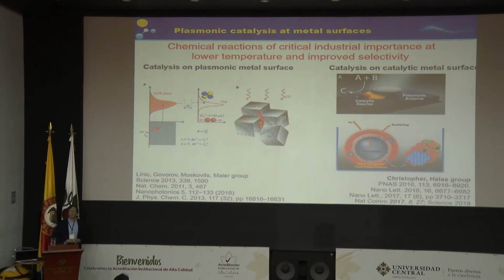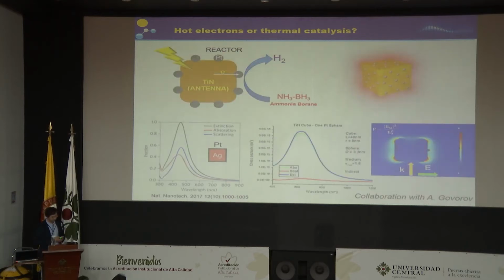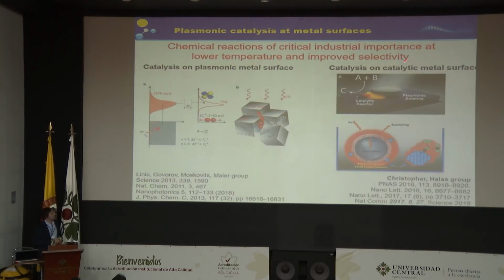Usually plasmonic metals are not very efficient catalysts, and therefore with this idea it's possible to combine the efficient concentration of light. So we use really an efficient antenna, like for example silver, and we put a small particle of catalytic material just aside. For example, palladium, rhodium, platinum, all these transition metals are very good catalysts.